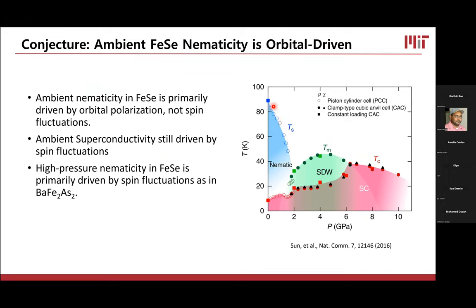In this case, we would have this piece of the phase diagram where nematicity is driven by the orbital degree of freedom. And under pressure, we get a different kind of nematicity and spin density wave, which is more spin driven. So we would have our ambient pressure superconductivity, which doesn't interact very strongly with this nematicity. And that could explain why the orthorhombicity isn't suppressed once we enter the superconducting state. And it also would allow this superconductivity, even under ambient conditions, to be driven by spin fluctuations, as we saw that spin fluctuations suppress in the superconducting state. So these different pieces of data do actually fit together pretty well in the schema of orbital-driven nematicity in iron selenide. So now I'm going to take you through the X-ray data that we use to further support this idea.